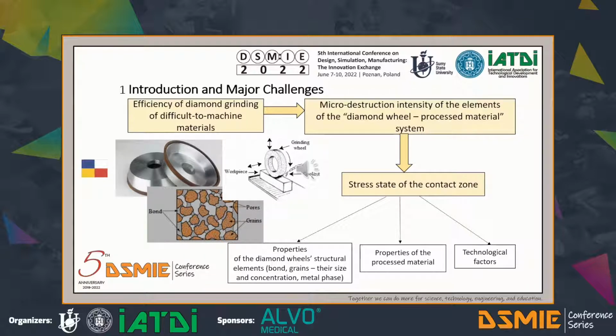When optimizing the stress level in the local cutting zone in order to increase the efficiency of grinding, it is necessary to take into account the characteristics of all elements of such a complex system: the diamond wheel structural elements, bond, diamond grains, their size and concentration, the metal phase in the grains, and properties of the process materials. The influence of technological factors of grinding should also be considered. In the system of bond, diamond grain, metal phase, and process material, the elements whose properties can be varied over a wide range are the concentration of diamond grains and the type of wheel bond. Therefore, the main attention was paid to the role of these elements.